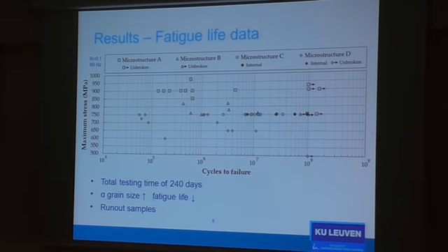So this is an overview of all the fatigue testing. The first thing I can tell you is that making this graph took a fatigue testing time of 240 days, because we tested 60 Hz only, with an R ratio of 0.1. And that doesn't include the tests that failed, so the ones that broke inside the clamps. Those are excluded, and I didn't include the preparation time.